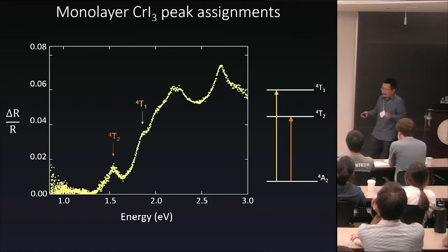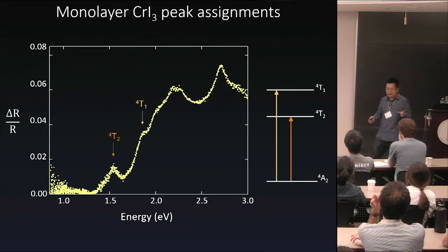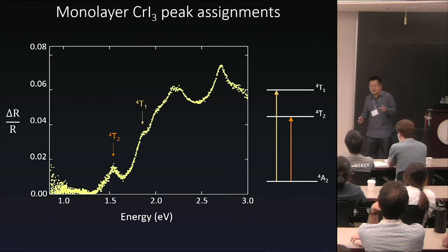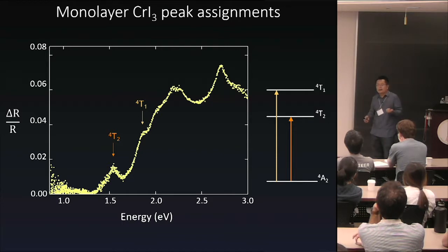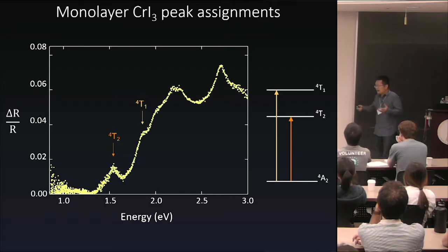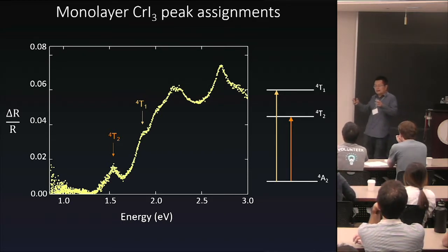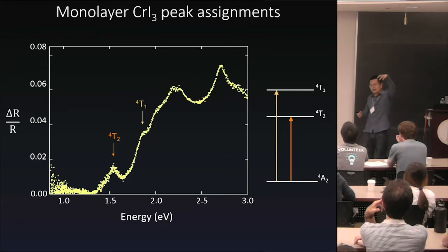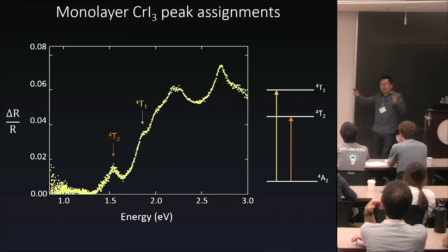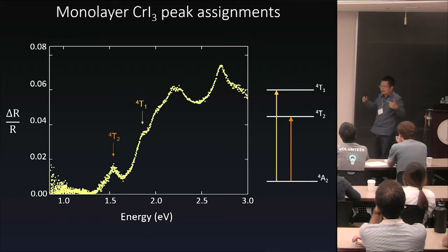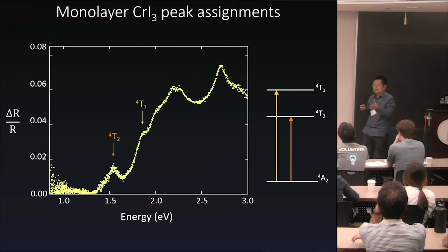The reason, as I just mentioned, is that D to D transition is actually symmetry forbidden. But the reason we can see this D to D transition here is, first of all, there are anisotropic phonons. Anisotropic phonons can break the local symmetries. The second, which I'm going to show you a little later: if you look at the top of the crystal structure, there are 6 chromium atoms next to each other in a hexagonal lattice structure. Between chromium and chromium there's an exchange field. This exchange field is anisotropic. It can also break the inversion symmetry in these octahedral unit cells.